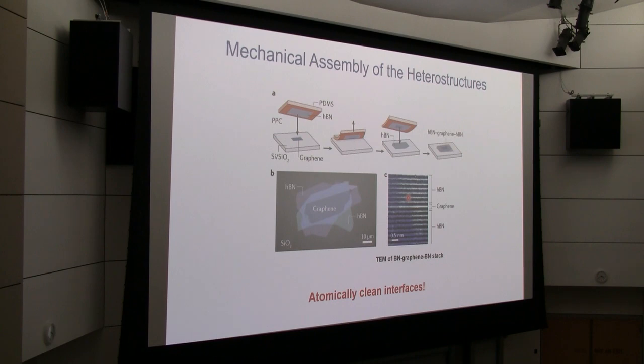Or when you just do everything in ambient condition without UHV, you are actually able to make this stack of atomically clean materials. And what happens, which very fortunately, is when you stack these 2D materials, those dirty things are not bonded strongly on this Van der Waals material. So they actually get pushed away. So as a result, after you assemble them, you can actually find the regions that are perfectly clean heterostructure.